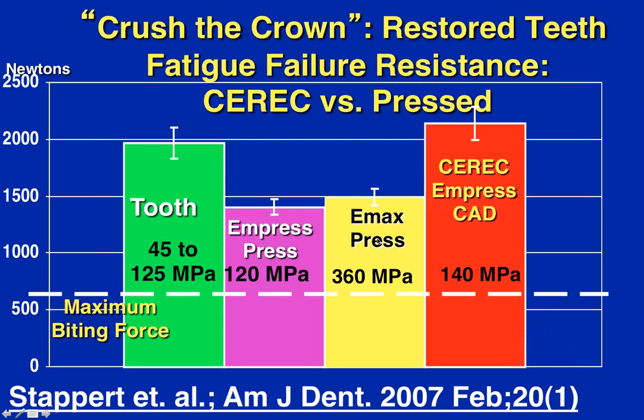A very interesting demonstration of, again, how strength is not the be-all and end-all of materials is looking at a study that was testing the material's reinforcement of natural tooth structure. So what this study did was they took a bunch of natural teeth, they basically crushed them, and you got a load to failure of around 2,000. They restored natural teeth with various pressable materials with different strengths. You see the Emax press at 360, and they also restored it with a monolithic Empress CAD crown as well. And the monolithic material that was bonded in, even though it's much weaker than the Emax press, which was also bonded in, gave you a very high value for the monolithic material compared to the higher strength material. So again, we focus too much on strength and not enough on actually how these materials are used.